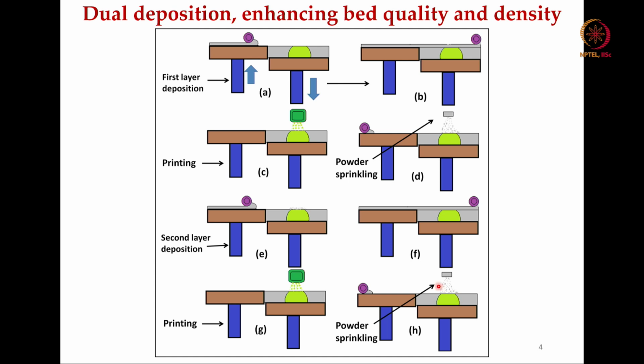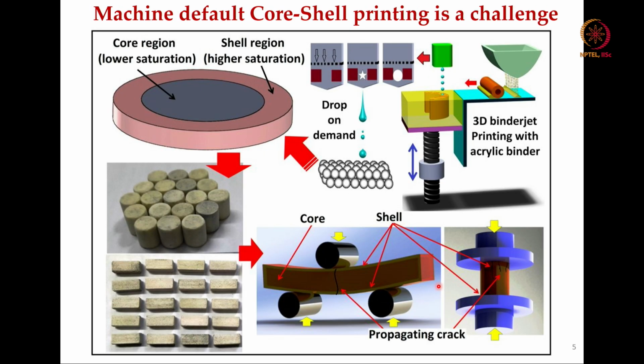So, powder bed quality is very important in contributing to good properties of the 3D binder jet printed construct. If we revisit the core shell methodology, the core is essentially the region where there is a lower saturation, and the shell is the region where there is a higher saturation. That is very characteristic of the conventional binder jet 3D printing process.